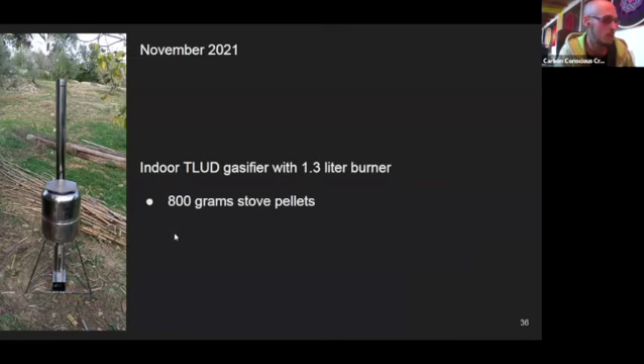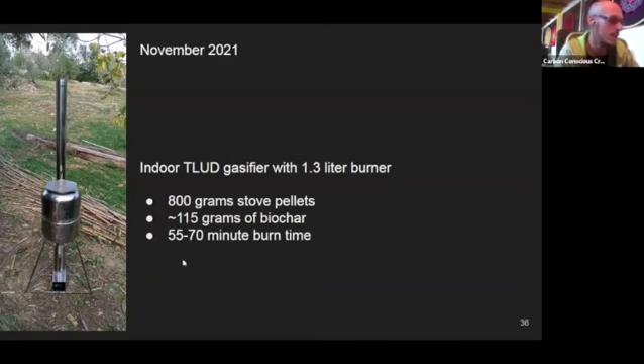1.3-liter burner. It runs on 800 grams of stove pellets. Gives about 115 grams of biochar. Takes about 55 to 70 minutes to burn. And this is very dependent on the atmospheric conditions. Like on some days, 55 minutes is the average time. But some days when the air pressure is a bit different, then the burn can take a lot longer.